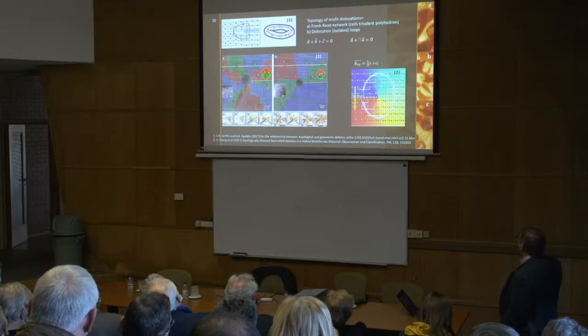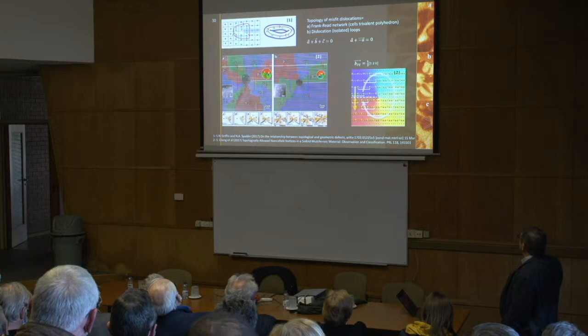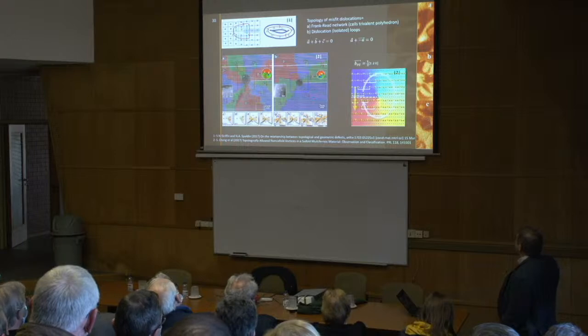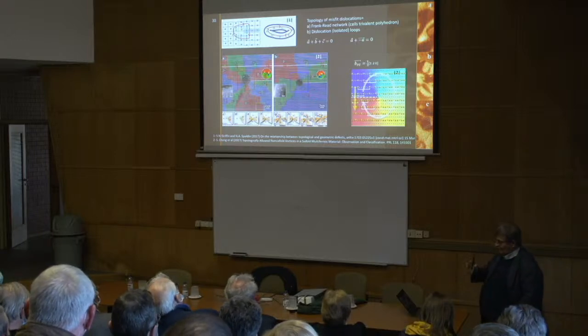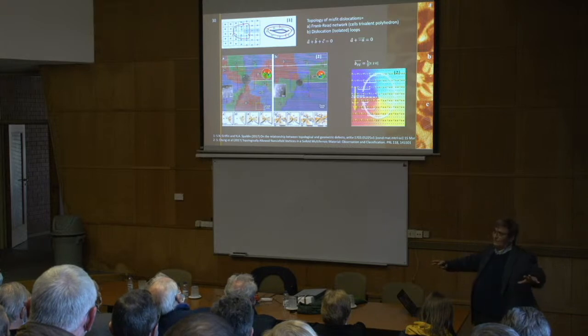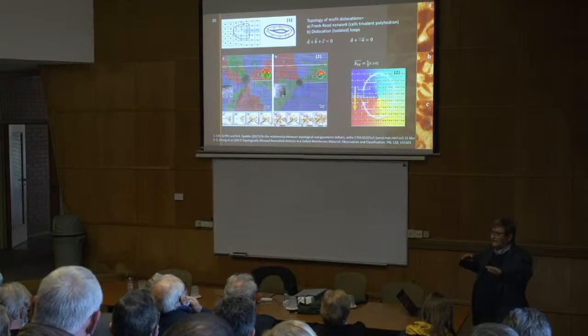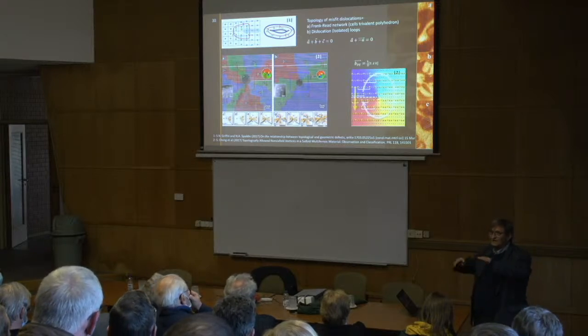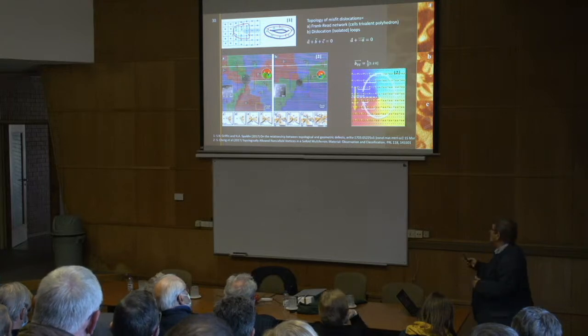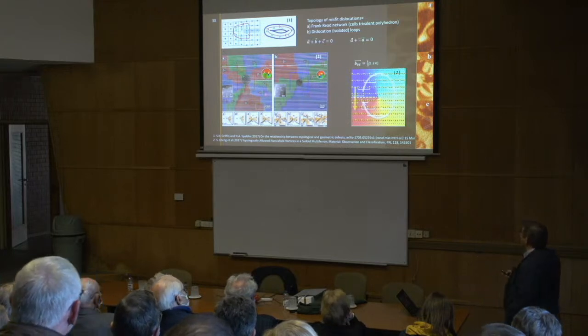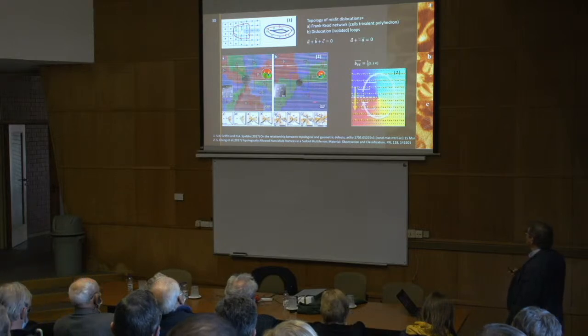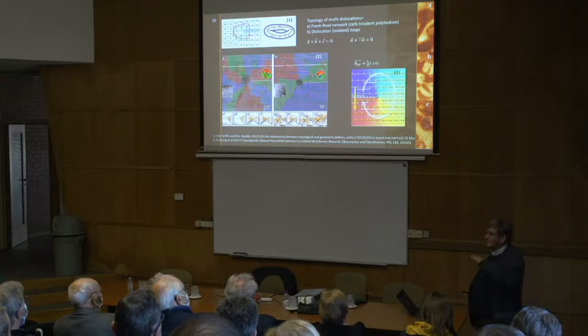STEM result. This dislocation just moves the phase one unit in that space of phases. This is a very nice picture from Cheng, and microscopes nowadays are used to the limits. We can go around the STEM image at a resolution of 0.7 angstroms more or less, and see how much atoms have statistical shift here and there and where they have shift. So these dislocations that existed here and change the number of phases are easily detectable if we get an image of this quality, a sample of this quality, a thin section of this regularity.